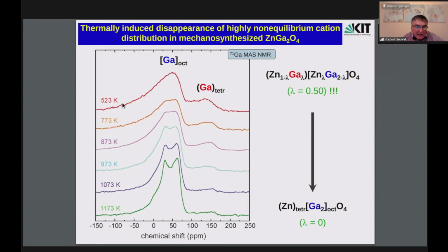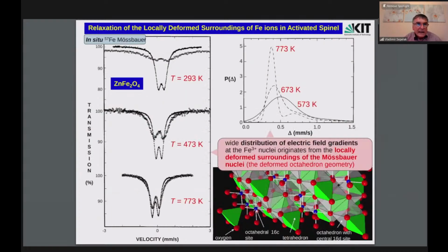with increasing temperature of thermal treatment, we see a full relaxation or disappearance of this inversion to the state where gallium cations occupy only octahedral sites, and it is typical for conventionally prepared bulk zinc gallate with a degree of inversion 0, I mean normal spinel. This is the in situ observation of the relaxation of the locally deformed surroundings of iron ions in zinc ferrite.